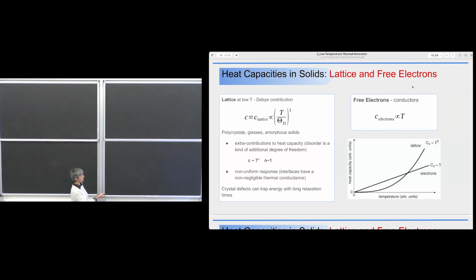And you see that this contribution scales with the third power of temperature. So it goes down to low temperature in a rather fast way. If you do not have a perfect crystal, you have additional contributions. So you may have polycrystals, glasses, amorphous solid, and whatever. You have extra contribution to the heat capacity. In some case, this contribution can be defined with a dependence on the temperature that is more or less linear, and so on.